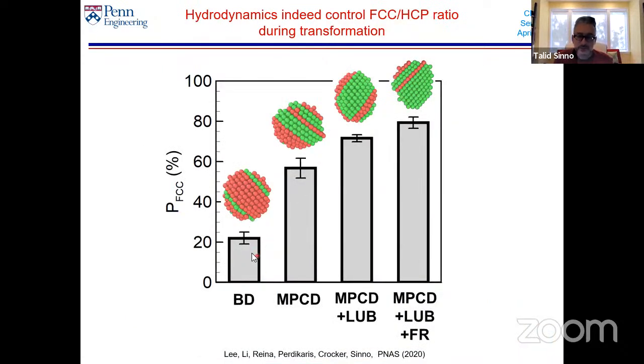So, and indeed, we took our base case Brownian dynamic simulations. This is the percentage of FCC that you see. And like I said, it's roughly 80-20 without hydrodynamics. We went to MPCD and we saw that now we went from 20% FCC to 60% FCC, which is still not 100%. And after some more thought, we started realizing that MPCD doesn't capture short-range interactions very well. There's a lot of technical reasons for that. It's a problem we're actually still working on. As we introduced some approximation for the lubrication forces between the particles, we got closer and closer to 80%. So it's clear hydrodynamics does bias this process.